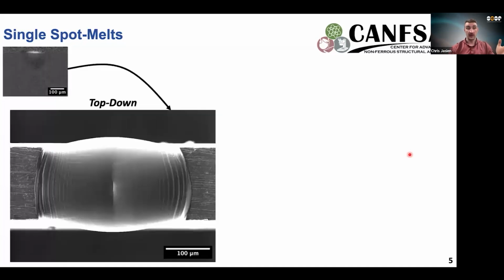So we started with our easiest experiment, a single spot melt, just shown up there, just to remind you what it looked like. And so when we look at it after it's solidified, from the top down, we see our material that was melted here, and then our substrate that wasn't melted, and we see what we would expect to see.